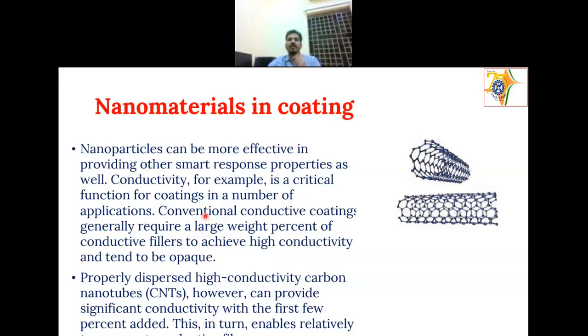The application of CNT, especially carbon nanotube and graphene, is especially for zinc-rich coating. The zinc-rich coating is one of the traditional coatings that have been used for protecting the industrial paint scheme, at around 75 to 80 micron thickness. The criterion for a zinc-rich coating to protect the underlying surface cathodically is that it should have a minimum of 80 weight percent of zinc in the dried film. So it's a large amount of zinc being used here. At the same time, it was found that out of the 80 percent, during the lifetime of the coating only 60 weight percent or 55 weight percent of zinc is used. The remainder is unused. So you're wasting a lot of zinc, and the zinc is sometimes released into the aquatic system, affecting aquatic life also.